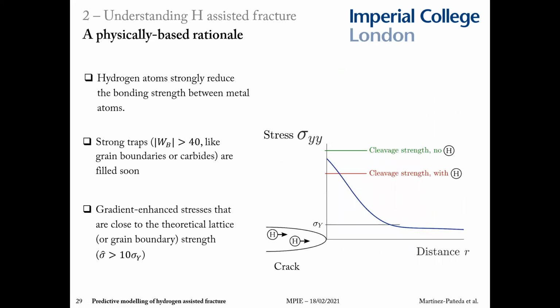And then when you properly consider the stress level near the crack tip, you see that the drop in cleavage strength is sufficient to trigger brittle fracture. Or in other words, when you combine the fact that the hydrogen will drop the cleavage strength, let's say by 20%, with the fact that your stresses at the critical distance are going to be close to the cleavage strength, maybe 9 times the yield stress, as we saw in the DDD simulations, then you end up with a mechanistic model that can predict the ductile to brittle shift as a natural byproduct of the simulation without any ad hoc criteria or fitting parameters. Because you don't have stresses or energy that is big enough to hit the cleavage strength, but the moment hydrogen comes into the picture, you are able to naturally predict that. And I will show this later.